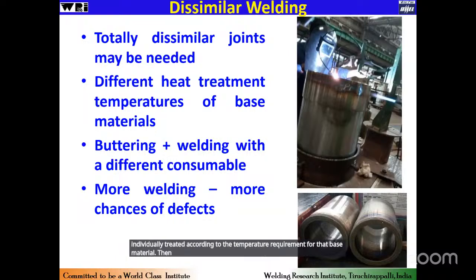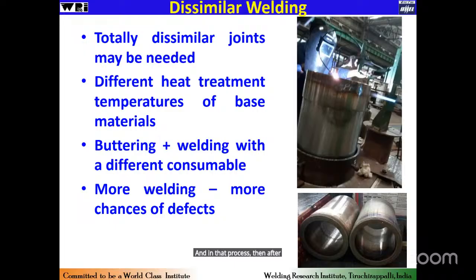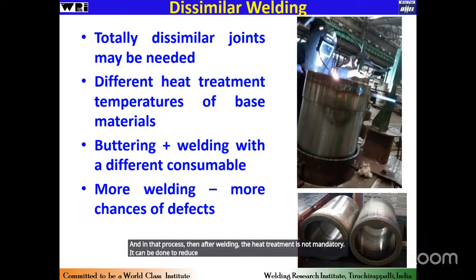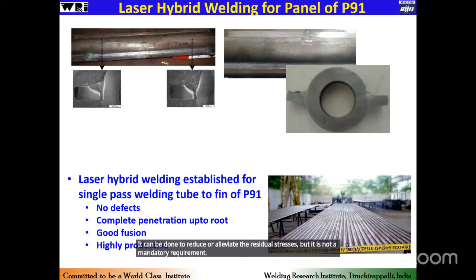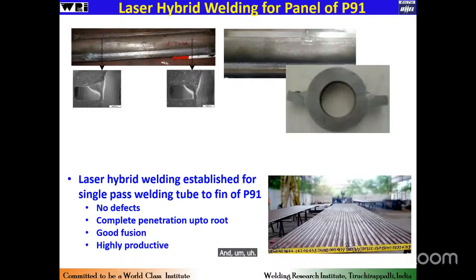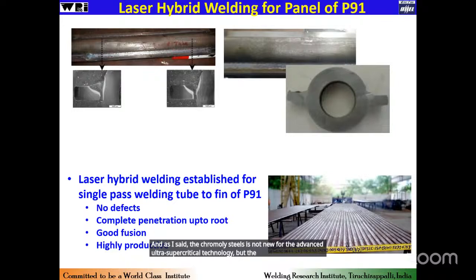Then the edge preparation will be done, and similar welding between the butter to butter layer will be carried out with the buttering consumable. And in that process, then after welding, the heat treatment is not mandatory. It can be done to reduce or alleviate the residual stresses, but it is not a mandatory requirement. And as I said, the chromoly steels is not new for the advanced ultra supercritical technology, but the higher chrome moly steel in the panel fabrication is something new which has not been done earlier.